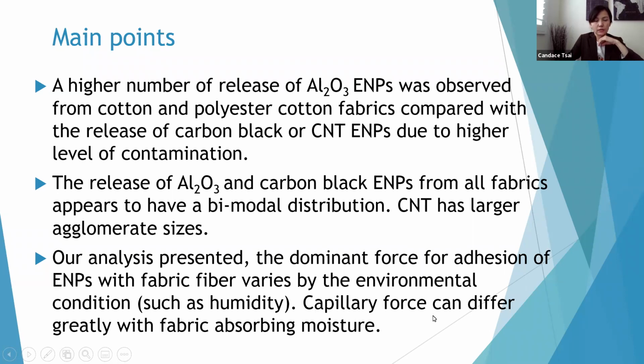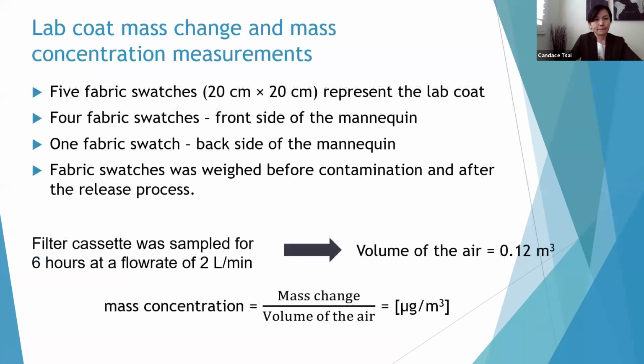The total surface interaction comes from the van der Waals force and the capillary force together, because the fabric absorbs moisture. If the fabric can absorb more moisture, it can actually release more particles.